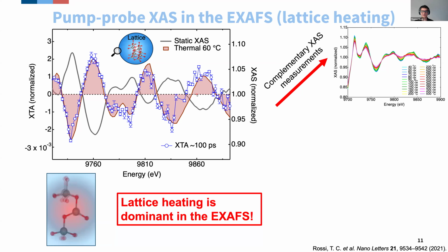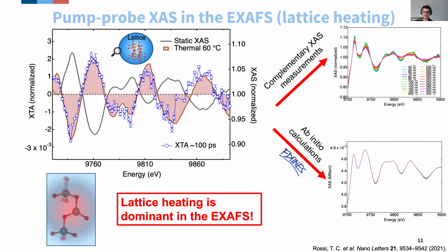There is another method that we can use that relies on ab initio calculation this time. We did a calculation in the full multiple scattering approach using the FDMNES code, where we also build a database by calculating many spectra when the Debye-Waller factor of the material is increased. And again, by doing a chi-square minimization, we find the best agreement with the experiment.